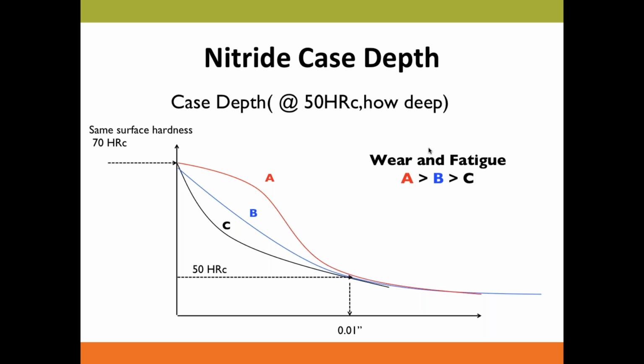First of all, when you do a hardness test on the surface, you will get 70. And when you ask for the certs, you will get 10 thou. But A, B, and C are going to perform differently because the saturation or the integrity of the nitride is different. A is better than B, and B is better than C. On top of that, when you want to check the quality of the nitride, it's a destructive method. That means you have to cut open your sleeves, and rarely will people do that. They will just trust their nitrider.